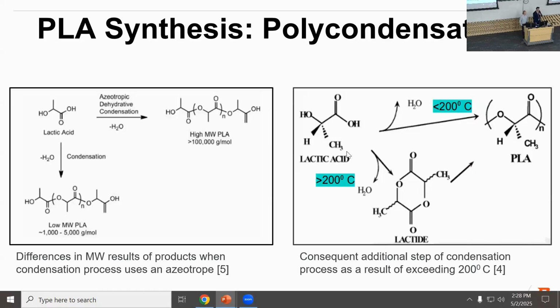The figure on the right shows why you would want to do this polycondensation process below 200 degrees Celsius. If it's above this temperature, you have an extra lactide formation step instead of going directly from lactic acid to PLA. It's not the worst thing, but it does hinder the efficiency of the process.